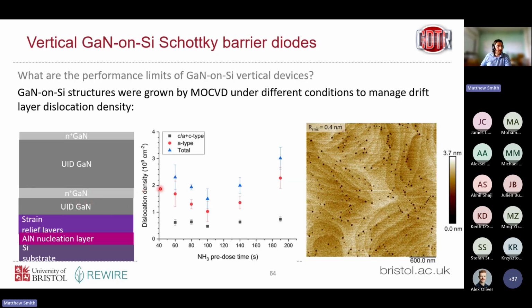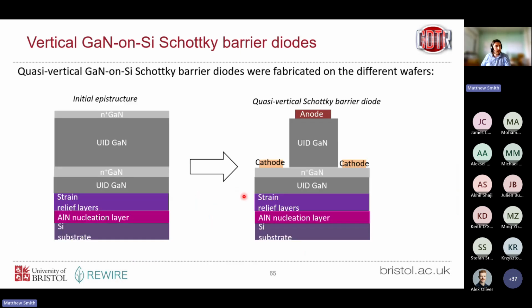So what we found was that we can control the dislocation density in the drift layer through the growth conditions. So this is the ammonia pre-dose time. It's how long we expose this substrate to ammonia for. We can see a dip in the dislocation density at some fixed value. So we made devices using these structures.